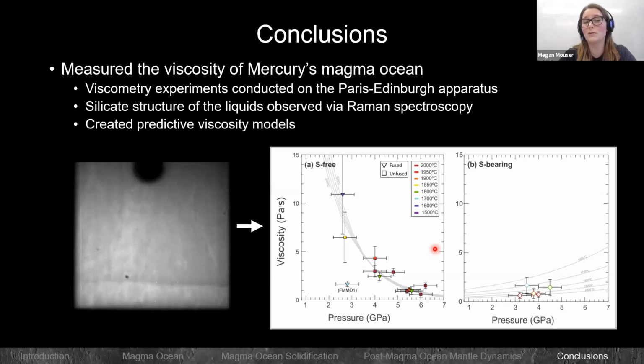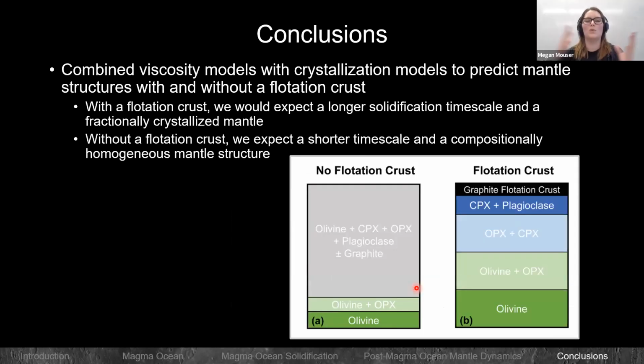So to start, we measured the viscosity of Mercury's magma ocean. We did that on the Paris-Edinburgh press, and we looked at the sulfur-free and sulfur-bearing compositions. And we took those liquid compositions, and we were able to extrapolate that to what this means for the evolution of Mercury's mantle and predicting basically what the crystallization styles would be on different solidification timescales. And so, we have some different end members that we could expect in terms of Mercury's interior.